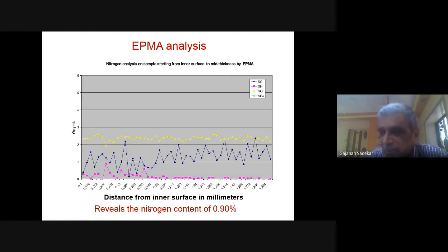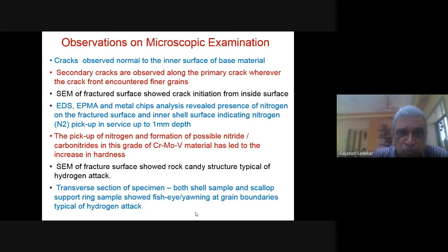Then we did the EPMA, the electron probe micro analyzer, which we use to know the composition of that particular substance. This is the distance from the inner surface in millimeter, and this is the weight percentage. So we checked whether nitrogen has gone into the surface. It reveals that the nitrogen content was 0.9%, which was not originally in the material. So that's a very important observation. If you look at the overall summary, cracks are observed normal to the inner surface of the base material. Secondary cracks are observed along the primary crack wherever the crack encountered fine grains.